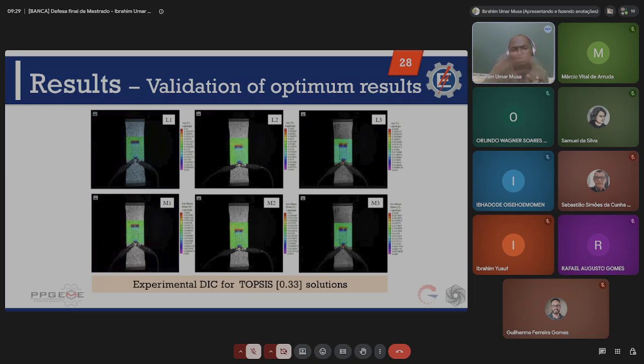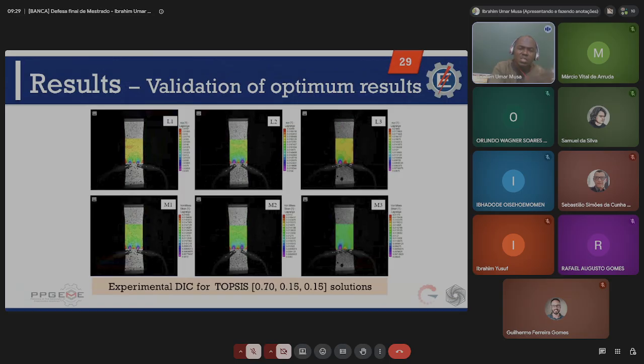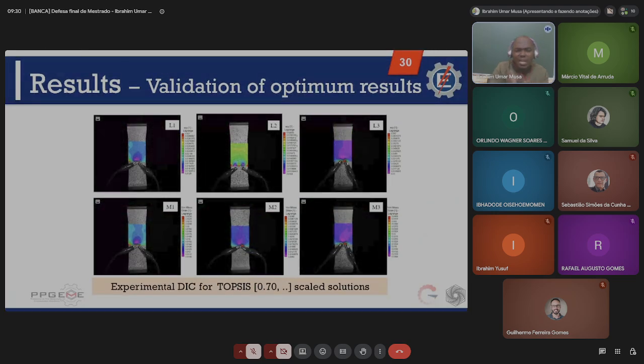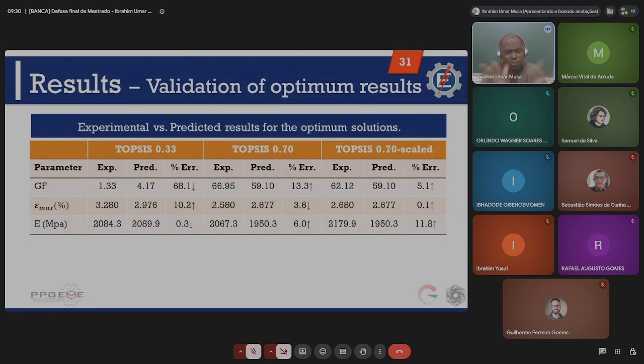We have these three different replicas of the test samples for the validation. And for the TOPSIS with special attention attached to sensitivity, we have it here, an embedded design. Because of the penalty identified with the stiffness for this particular design, that's the embedded design, we chose to scale down the geometry to see if that problem can be mitigated, and this is the result we obtained experimentally from the scaled variant. We have the entire validation results summarized by this table.